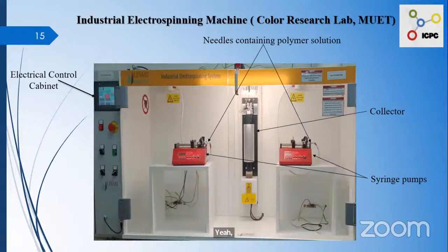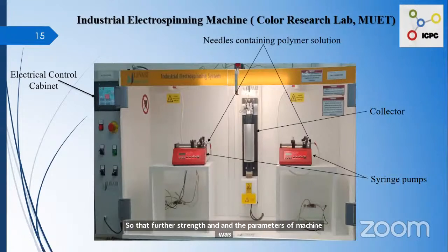So for the testing, the color strength and colorimetric values of the dope dye were assessed on a Datacolor spectrophotometer, and the parameters of the machine were set at sample aperture 9 mm, illuminant D65, standard observer 10 degrees, and ultraviolet and specular component included. Dope dye samples were also tested for color fastness.